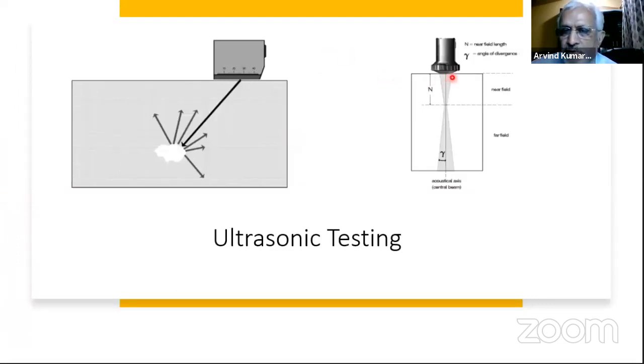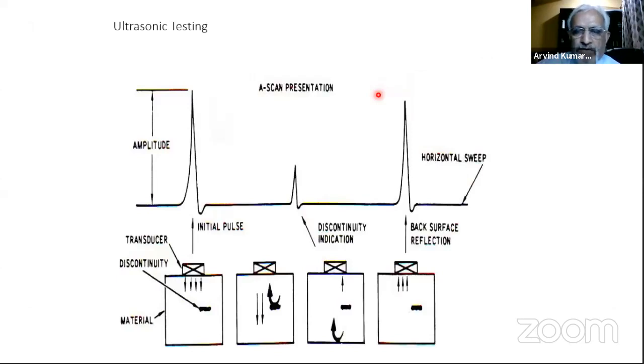So in a normal beam probe, we call this a near field effect, a near zone or a dead zone, where you are not able to pick up any indication, or it is not used to do any kind of testing because there are a lot of electrical disturbances within this region. So the testing is generally done in the far field, from here to here. This near field is reduced in the case of using a TR probe. So I explained how the waves interact with the defect.